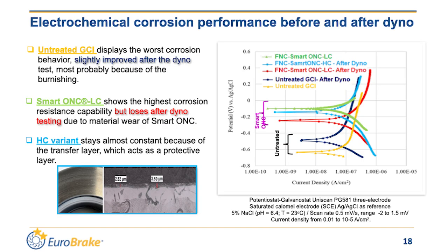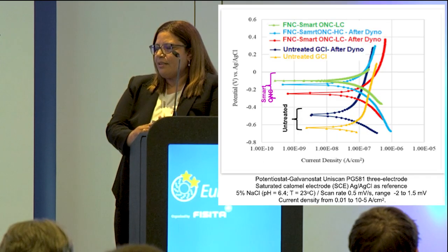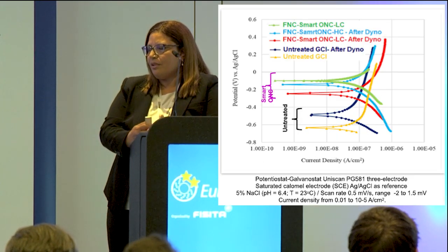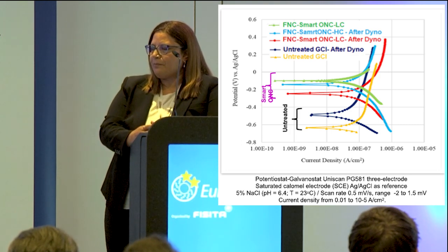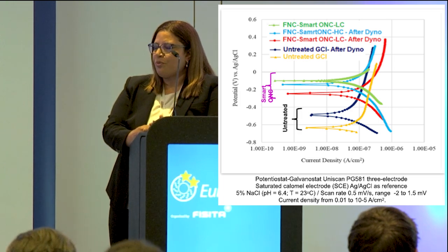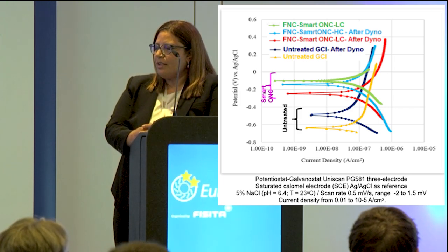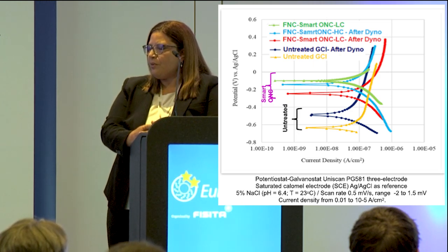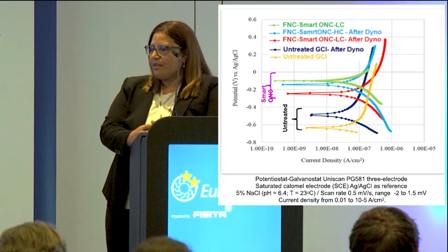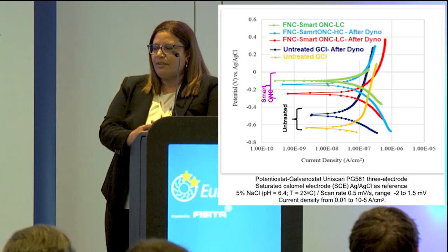We did also electrochemical corrosion testing to compare the performance of the corrosion resistance before and after dyno testing. The trend of the Tafel curves shows that the untreated gray cast iron, the yellow one, presents the worst corrosion resistance, which improved slightly because of the burnishing. And the Smart ONC variant shows a corrosion potential that shifted to positive values.